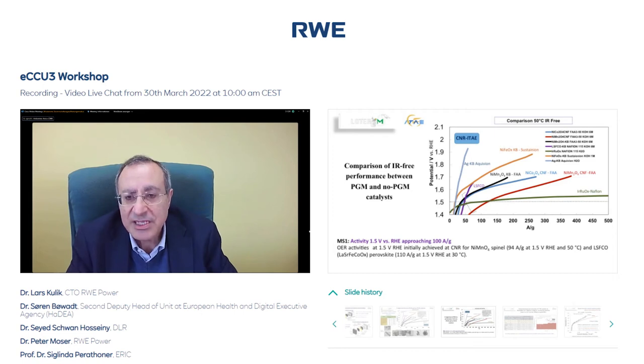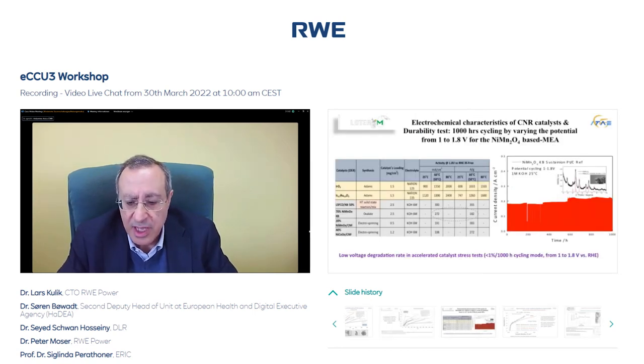Slide number five, please. So in slide number five, we can really see that at low operating potentials at 1.5 volts, that is just above the thermoneutral potential for the water splitting, usually we get interesting mass activities, something like 100 ampere per gram already with non-precious metal electrocatalysts. However, we also see that the best performance is achieved in the protonic environment using iridium, ruthenium oxide, oxygen evolution electrocatalysts. Slide number six, please.